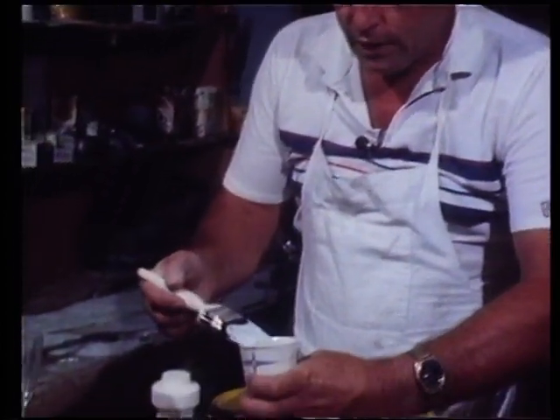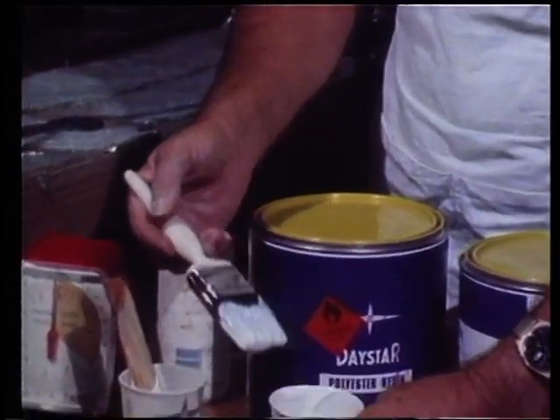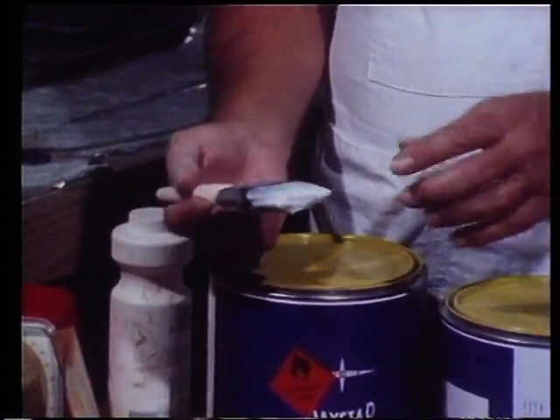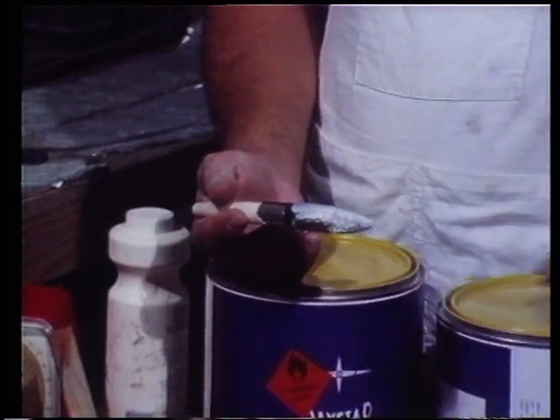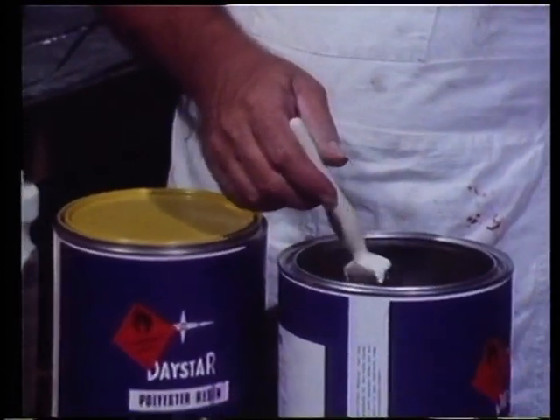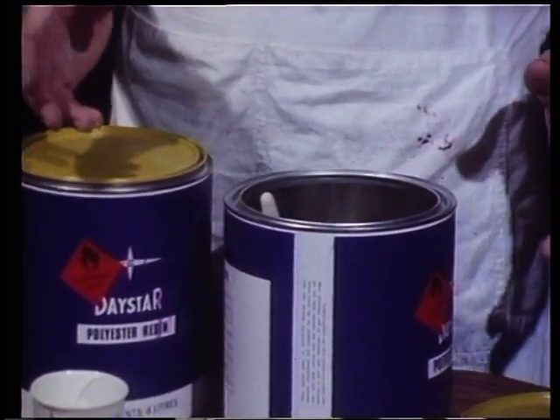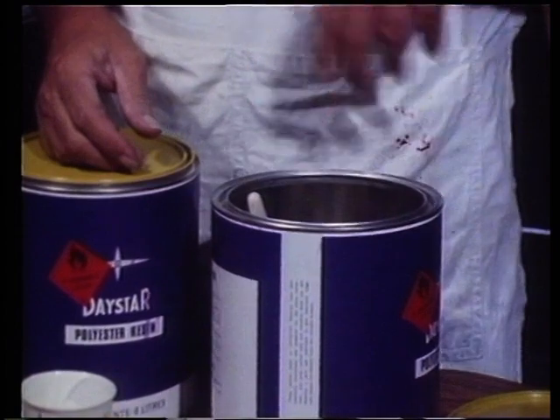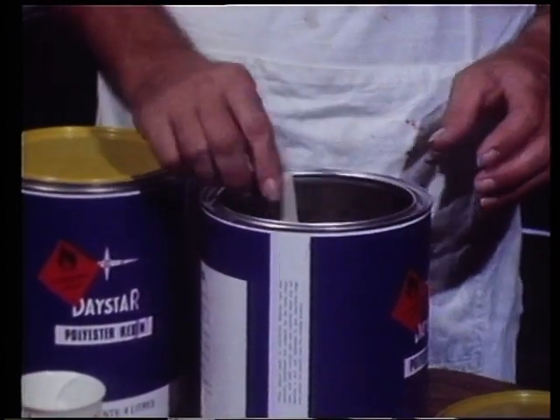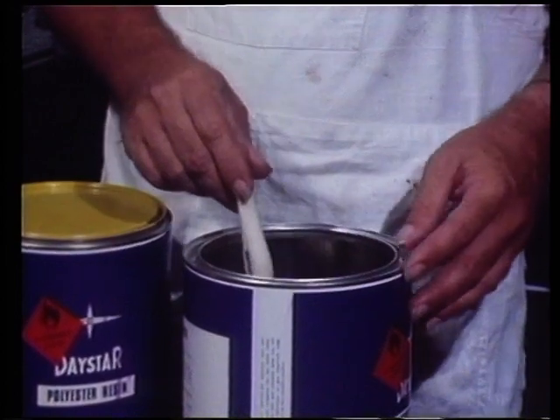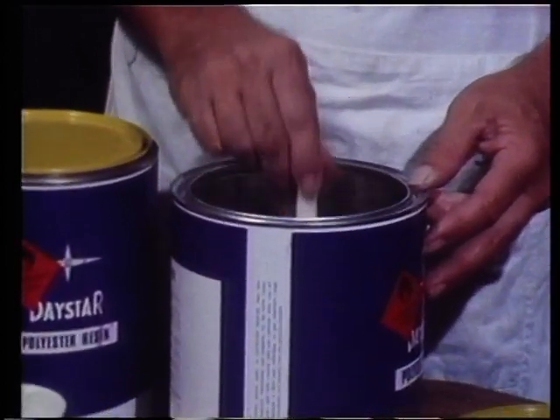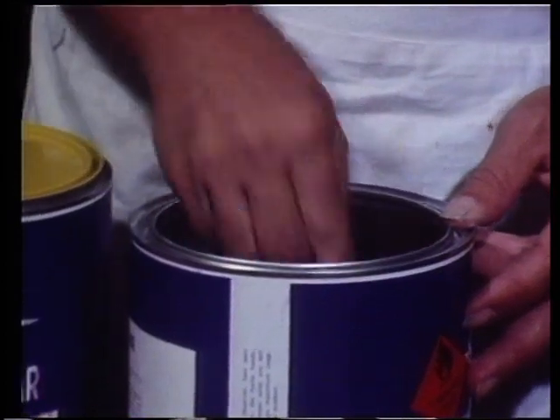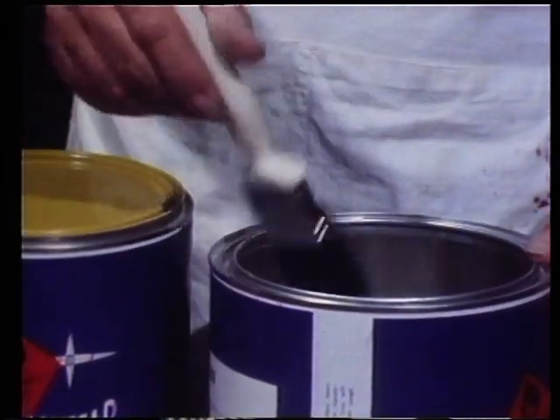Before we get into actually laying up the hull, there are a couple of things I want to tell you about the maintenance of your tools, particularly your brushes. Now this brush here is full of gel coat, catalysed gel coat. If we don't wash it properly and thoroughly, that gel coat will cure in there and ruin the brush. If I just drop that into the acetone, without doing anything, the acetone isn't strong enough to dissolve all of the gel coat in the brush, and it'll cure and we'll lose it. So whenever you're putting a brush into the acetone, your washing solvent, you always pop it up and down like that and make sure that you've cleaned all of the resin or gel coat out of the bristles.